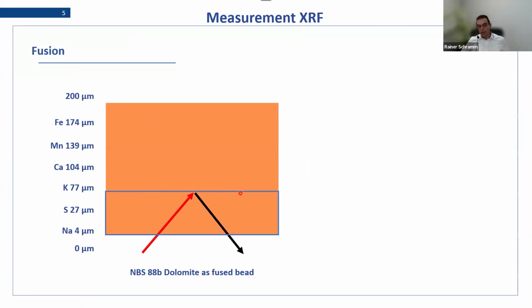But this means that if the total mass of that bead varies, it doesn't matter for the result for potassium, because the information of potassium is only coming from this volume here. And that means if here the thickness changes, it has no effect on our final result. So that's the first very important piece of information, that some elements are measured only from the surface, like sodium, and then with increasing atomic number, we go deeper and deeper into the bead.